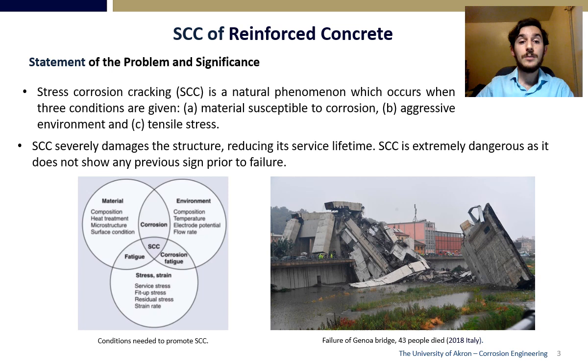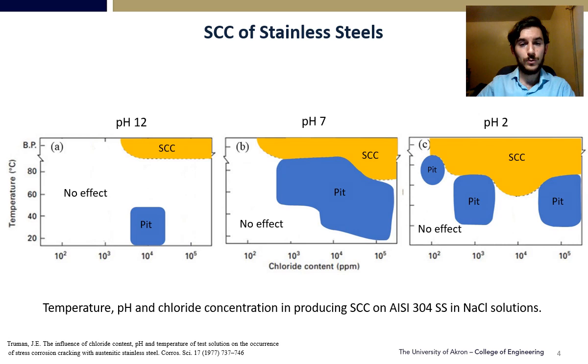Now, let's take a look at the requirements for stress-corrosion cracking to occur on stainless steels. As we can see from the study of Truman on 304 stainless steel, as we decrease the pH, the region for stress-corrosion cracking to occur enlarges, reducing the minimum temperature and chloride content required. However, for concrete, the pH is 12.6. Hence, we will need to be close to the boiling temperature, and during common working conditions, we will never reach that temperature.